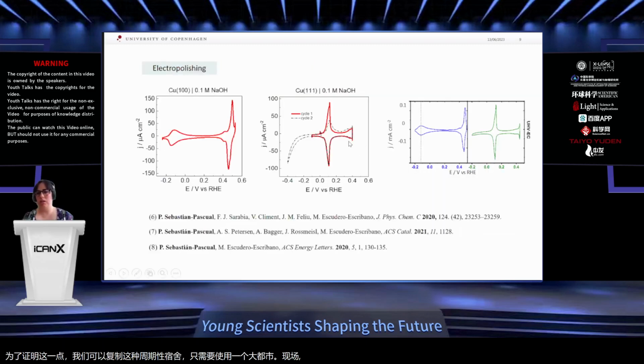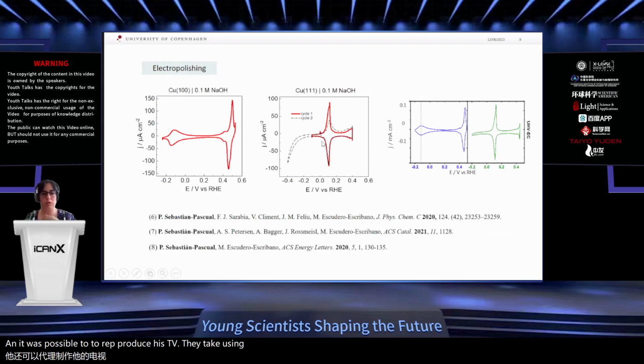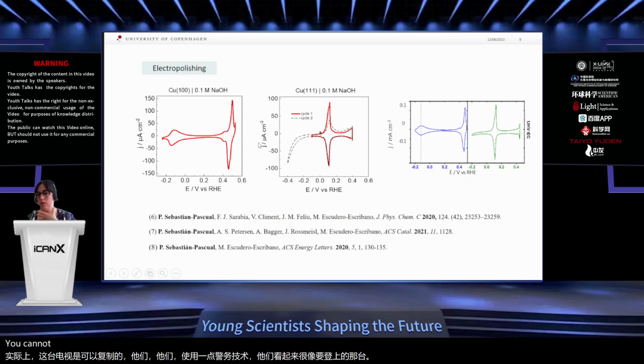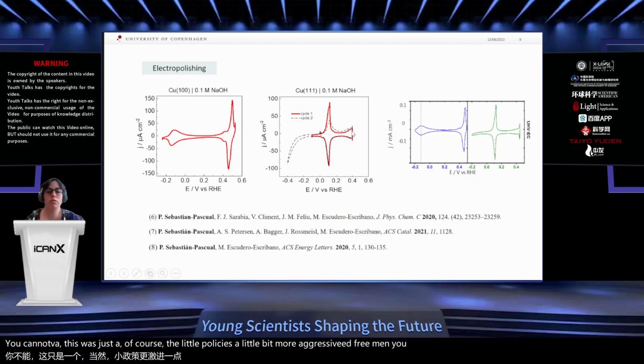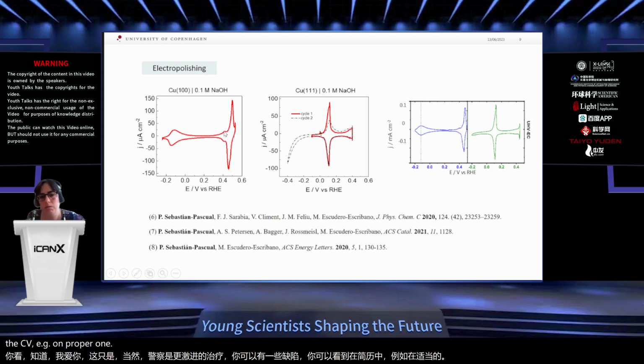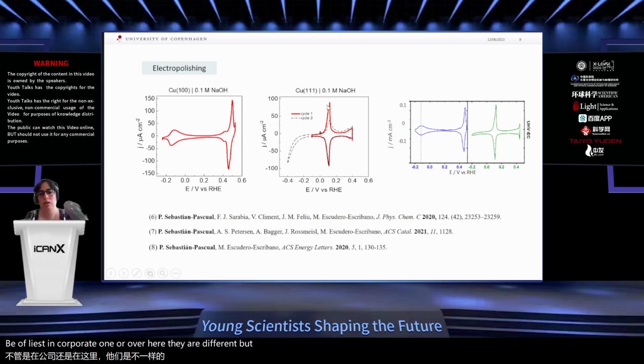And actually, it was possible to reproduce this CV. Using the electropolishing technique, they look quite similar to the ones reported using ultra high vacuum conditions, just that, of course, electropolishing is a little bit more aggressive treatment. You can have some defects that you can see in the CV. For example, on copper 111, here there are a few defects. On copper 100, here there are a few defects. But the features, the intensity of the features, are indicating that our surfaces are mainly 111 in this case, or 100 in this case.